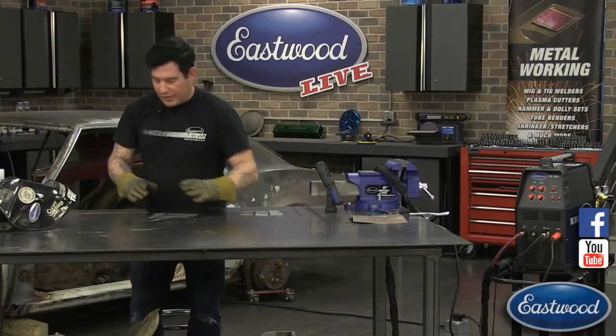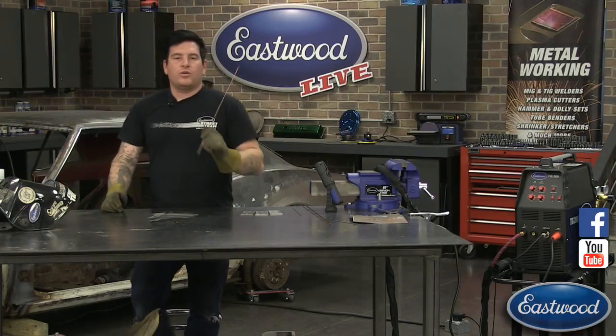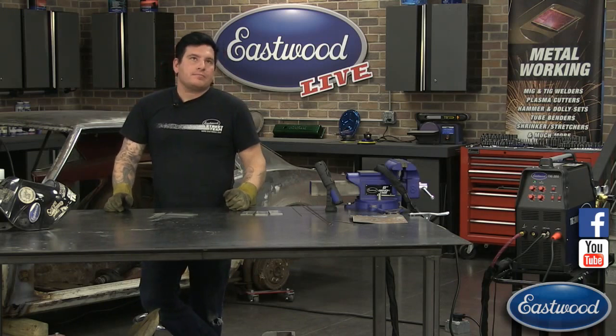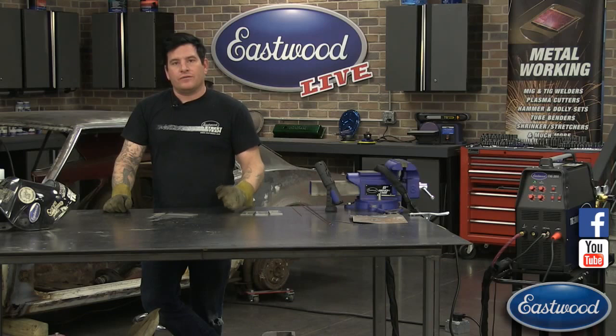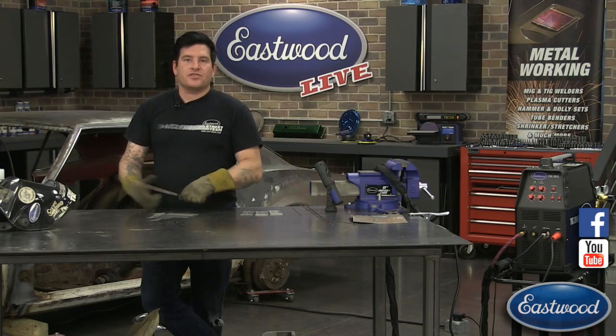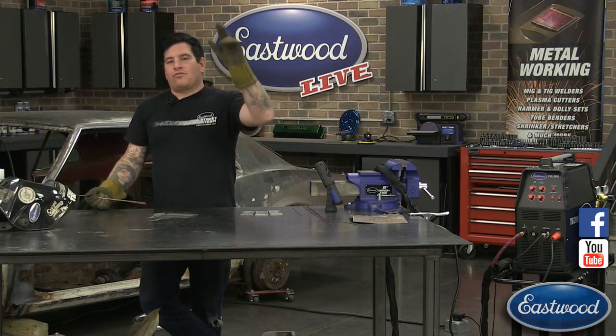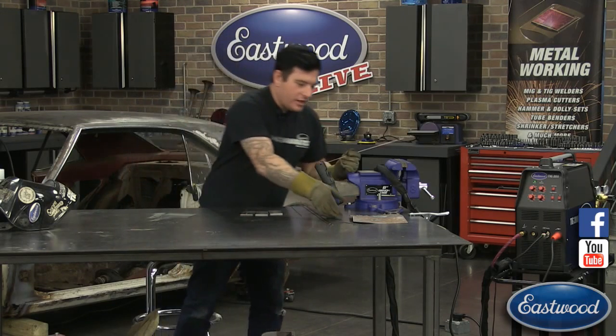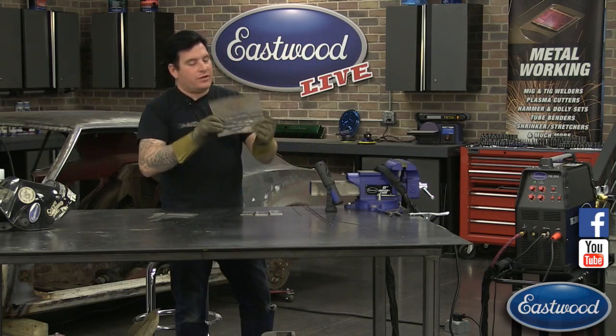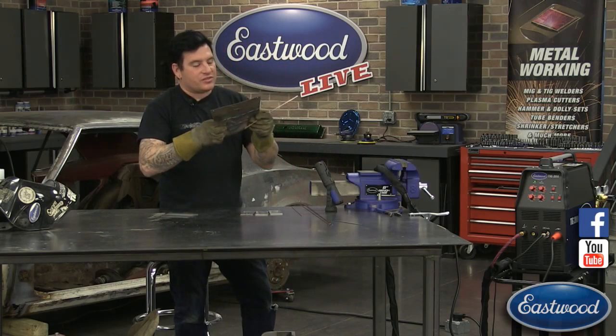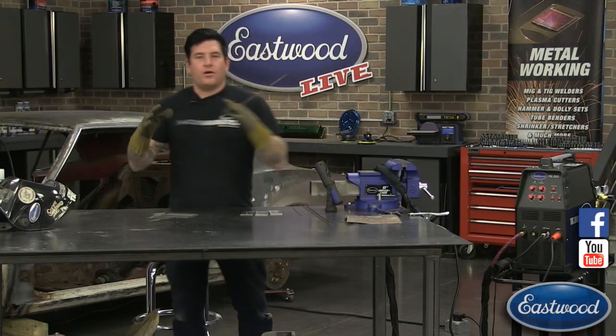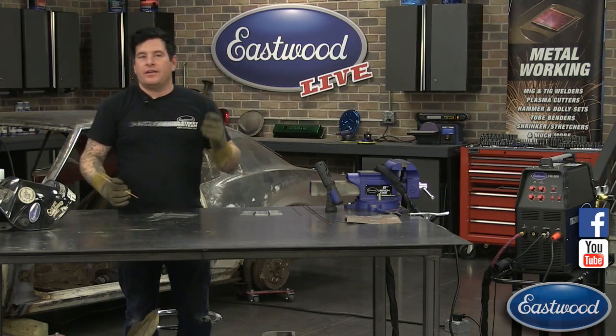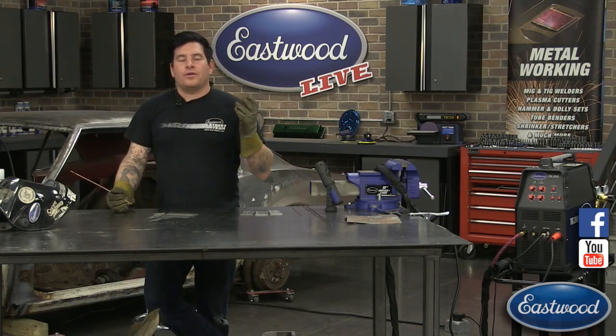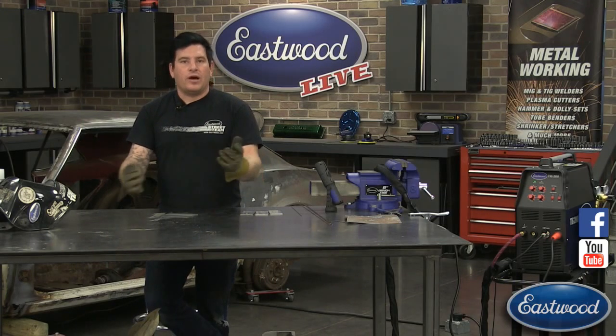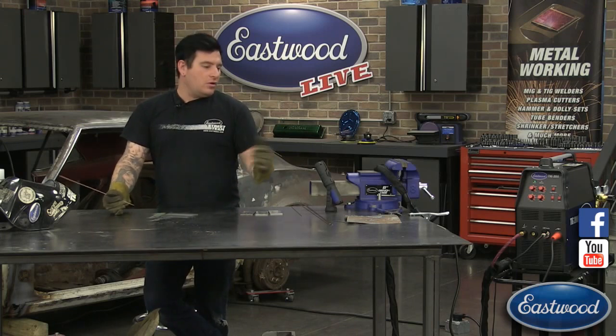What would a dirty weld look like? We had a question of what a dirty weld would look like. A couple quick ways you can tell. If you see pits in your weld, if you see little pinholes or pits, or like a little volcanic growth coming off of your weld. These are MIG welds. But if you see a little volcanic growth that comes up out of it after you weld, something's going on there. You don't have enough gas, or you possibly have something in your panel or not enough gas flow.